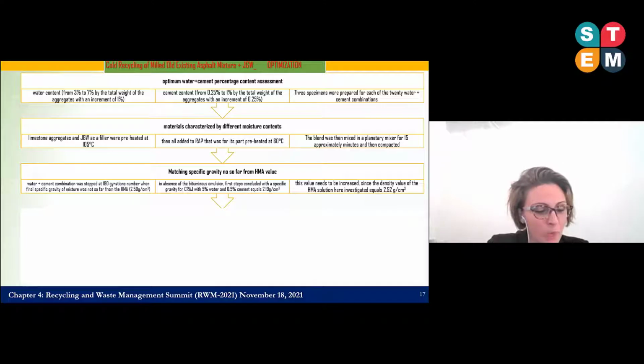So, firstly, we optimized the water plus cement content. Specifically, water percentage content from 3 to 7% by the total weight of the aggregates was investigated, combined with cement from 0.25% to 1% by the total weight of the aggregates. So we investigated 20 combinations of water plus cement values. The materials are characterized by different mixture contents. So we preheated the limestone aggregate, jet grouting waste, and RAP. The blend was then mixed in a planetary mixer for about 15 minutes, and then compacted using a gyratory compactor.